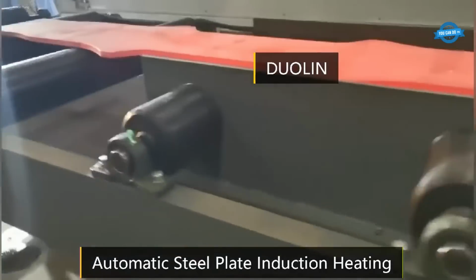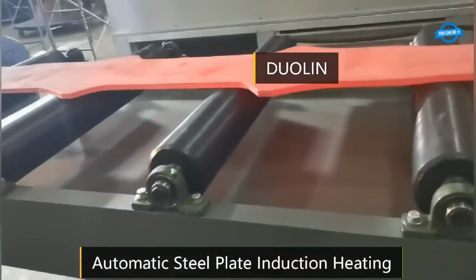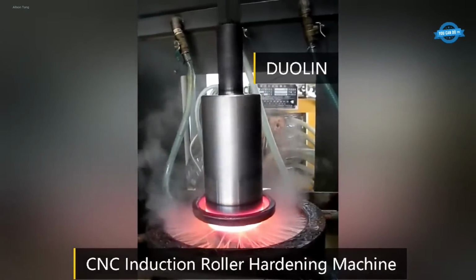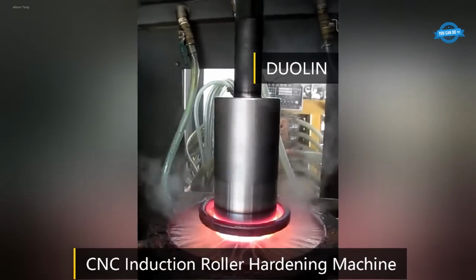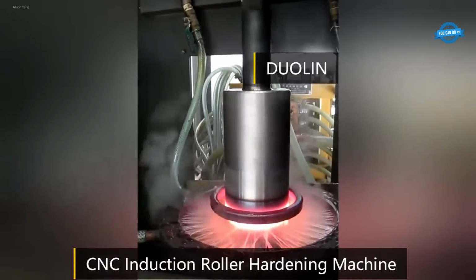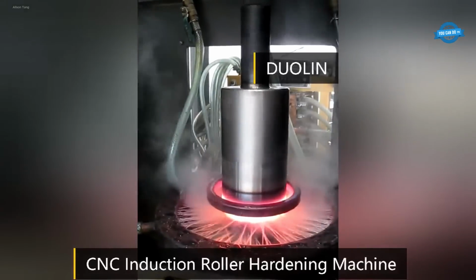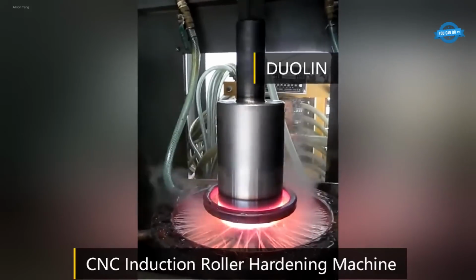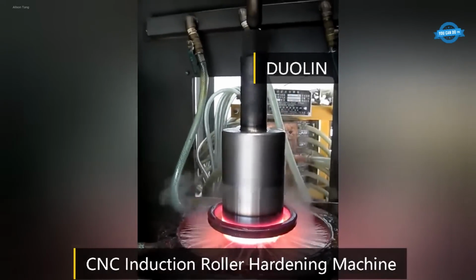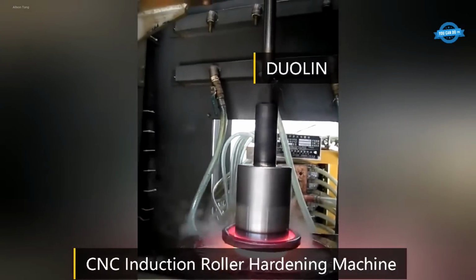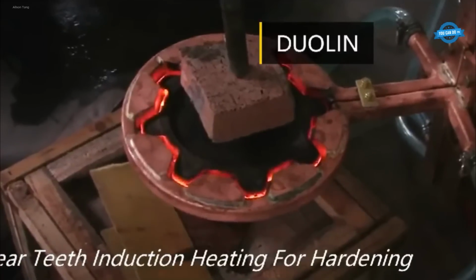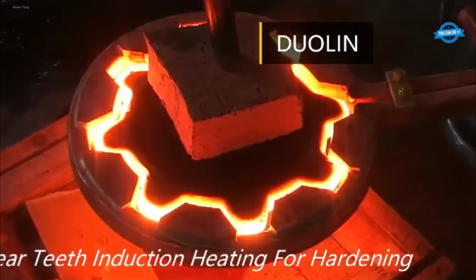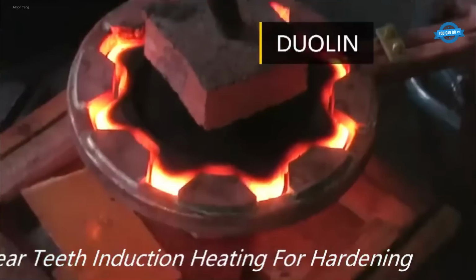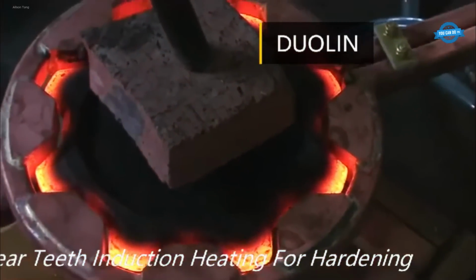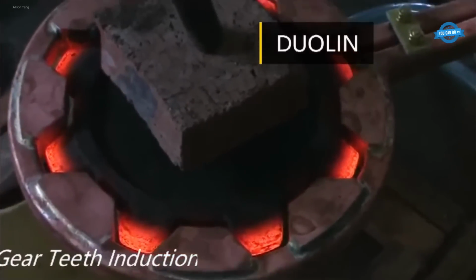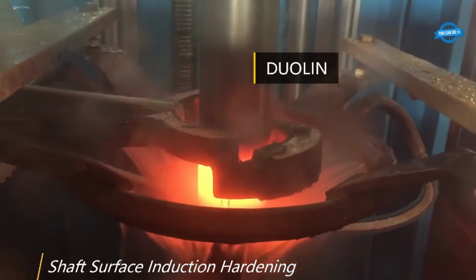The fully automatic induction heating line for hexagonal bar ends and carbon steel round bars ensures uniform, deep heat penetration, ideal for forging operations. Automatic steel plate induction heating systems allow efficient flat material processing with minimal thermal distortion. In surface treatment, Duolin's CNC induction roller hardening machines and shaft surface hardening equipment provide consistent hardening depth, enhancing wear resistance and fatigue strength. These machines are fully programmable for varied geometries and hardness profiles.